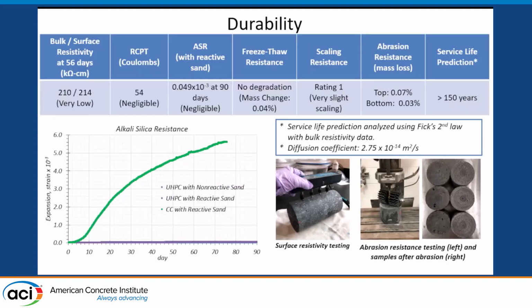So as we look at other information here, durability testing, I have just a quick summary. We looked at resistivity testing, rapid chloride penetration tests, ASR, freeze thaw, scaling, abrasion resistance, and then at the end we did a service life prediction. What we found is that all of these measures came out very well for the UHPC. Very low resistivity, negligible chloride penetration, and all the measures from these standardized tests were what we would expect for this type of material.